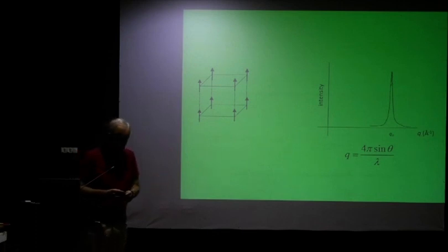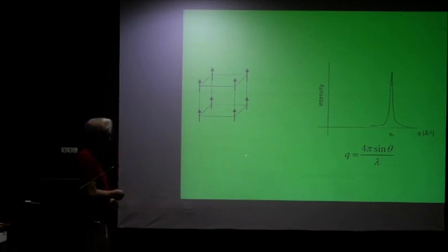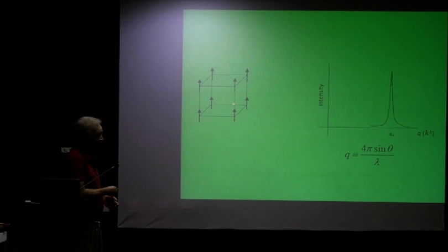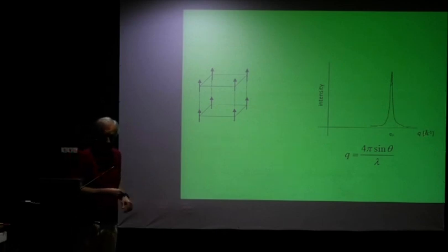It sees the magnetic structure as well as the crystallographic structure. If we have a structure like this, it's just depicted, where we have a ferromagnetic alignment on a certain lattice, then what you will get, when you do a diffraction, is the intensity over the Q. I wrote this as Q. You can write it as angle if you want to. It doesn't make any difference.